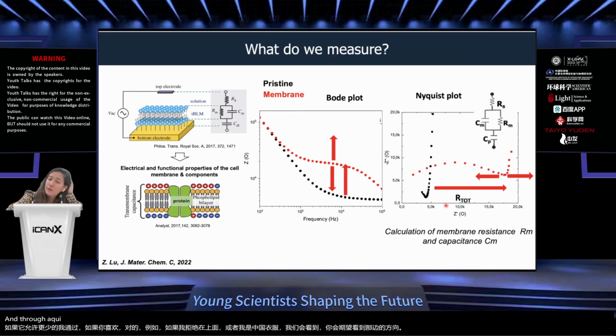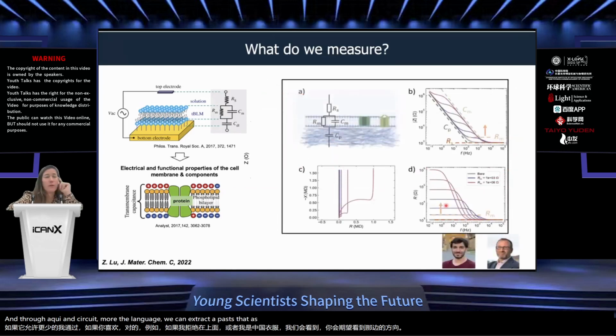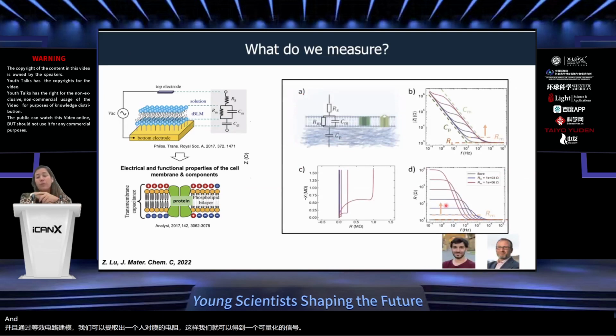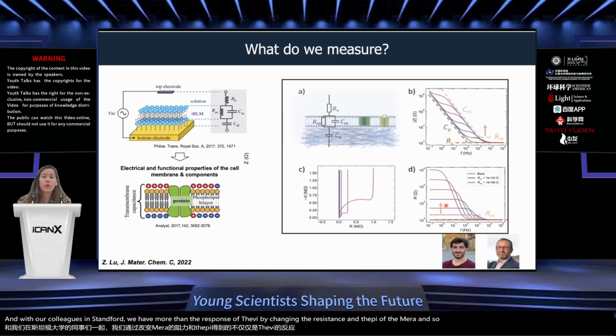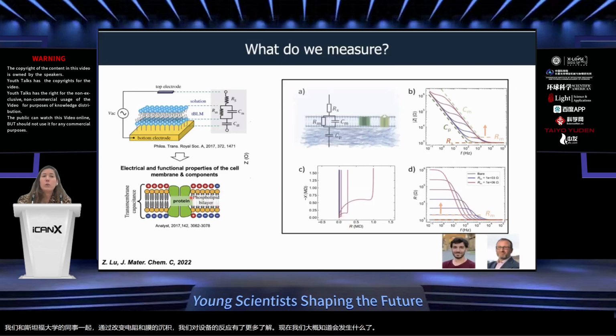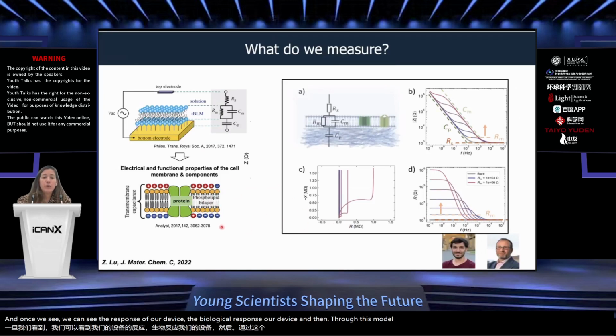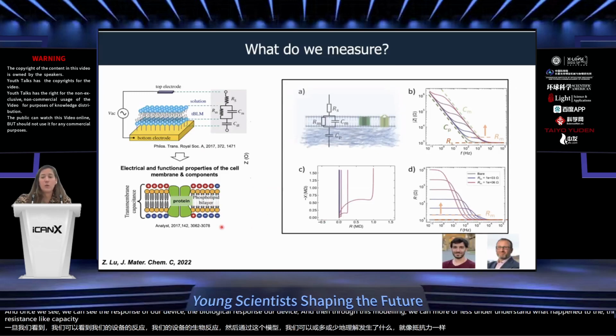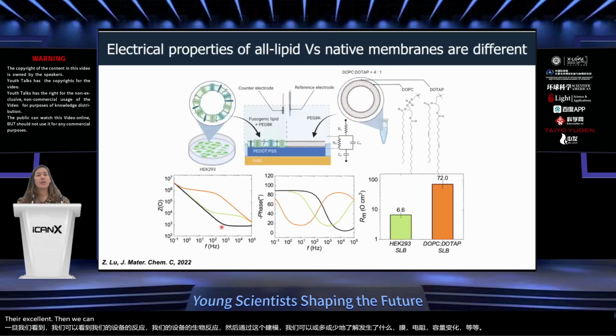And through equivalent circuit modeling, we can extract the capacitance and the resistance of the membrane, so we have a quantifiable signal. With our colleagues at Stanford, we have modeled the response of the device by changing the resistance and the capacitance of the membrane. And so now we know more or less what to expect. Once we see the biological response of our device, through this modeling we can more or less understand what happened to the membrane, whether the resistance or the capacitance changed, and in what direction. And then we can extract some biological information from that.